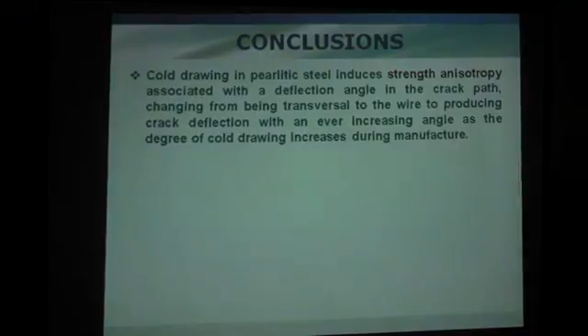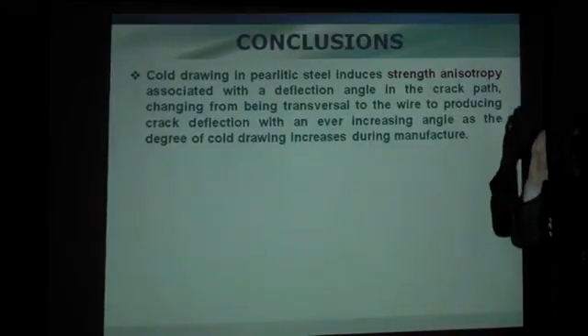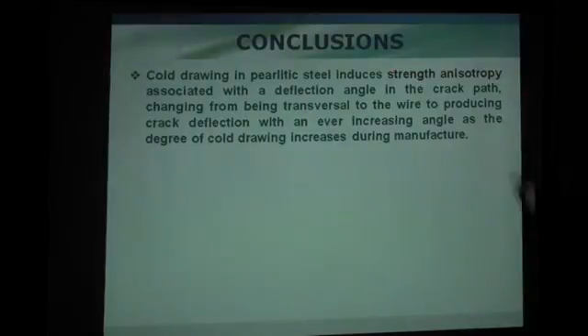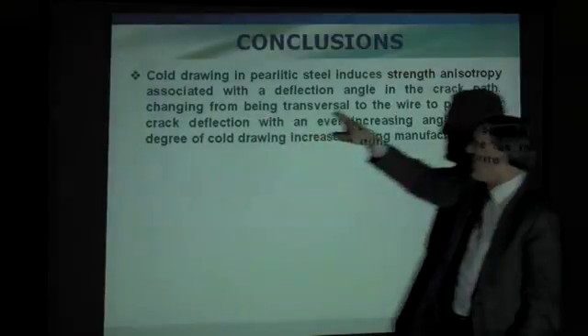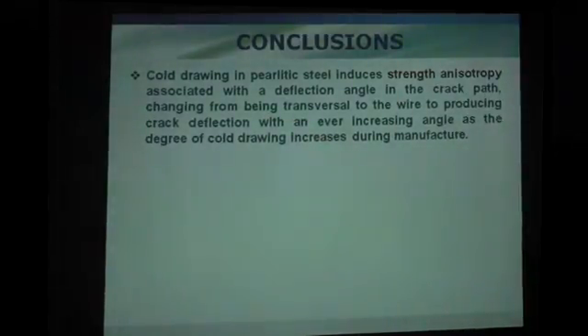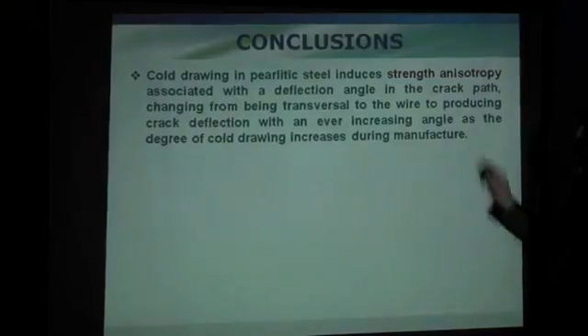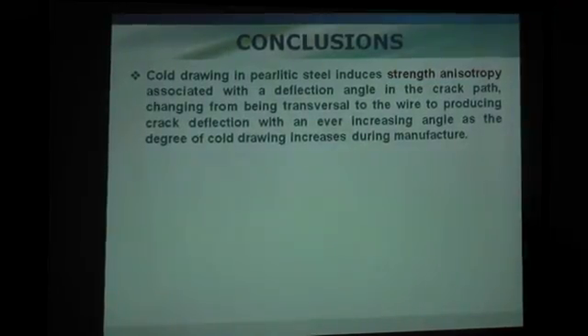And now let's go to the conclusion. The chairman is standing up, but we finish. Cold drawing in pearlitic steel induces strength anisotropy associated with a deflection angle. This is the debonding, the delamination in the crack path, the macroscopic crack path changing from being transversal to the wire axis to producing crack deflection with an ever increasing angle as the degree of cold drawing increases during manufacturing.